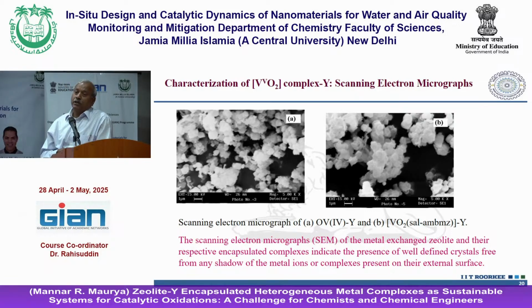If you have EDS attached, that can also give some idea, but it does not give a correct idea. The reason is that in a zeolite-encapsulated metal complex, your metal content is inside the cavity. If a pore or void is available, and the incident beam goes through it, it can give you some idea. So you will definitely see some metal content, but not 100%. That is the only problem, but still you can have an idea.